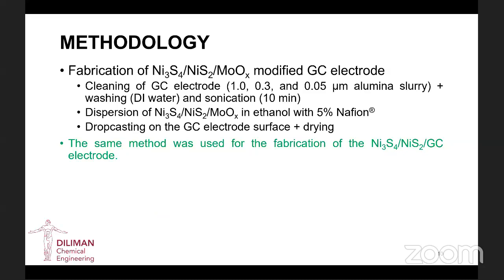So the next step is the fabrication of the modified electrode on a glassy carbon electrode, which consists of cleaning the glassy carbon electrode using alumina slurry, washing it with copious amounts of DI water using sonication. Then the prepared composite was dispersed in ethanol with 5% Nafion, which is the binder.